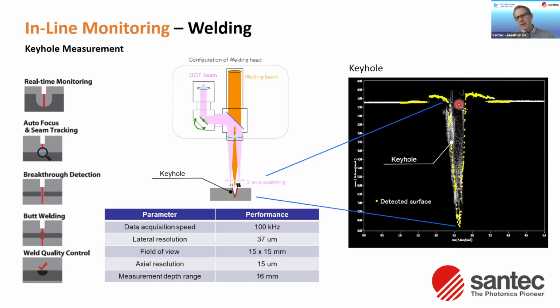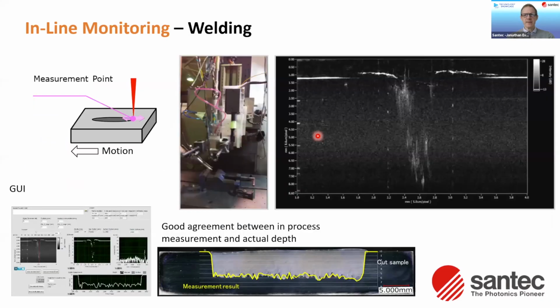Here you can see the OCT image of the keyhole using our system, and the algorithm pulling out the actual surface of the keyhole. We can see that in process here. I've got... the video is not playing, okay. Anyhow, what we did here was look at the measurement results during the welding process, which is the yellow line. Then we took the weld and cut it in half and compared the depth of the weld after the fact to the measured. You can see the very good agreement between the in-process measurement of the weld depth compared to the actual weld depth that was assessed post-process. So a nice use of this technology, inline process monitoring.